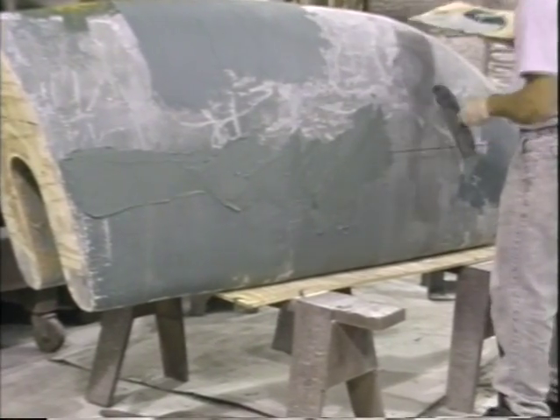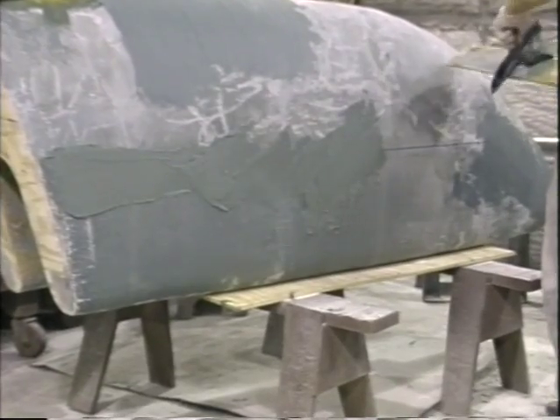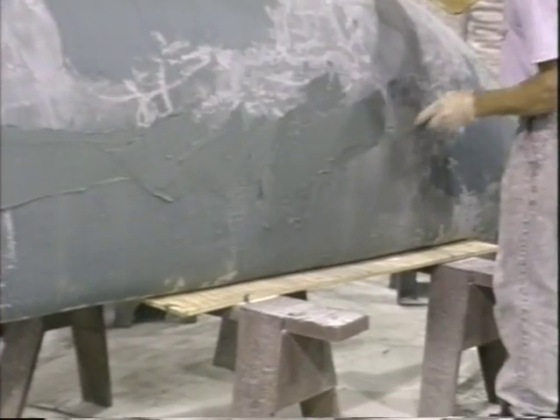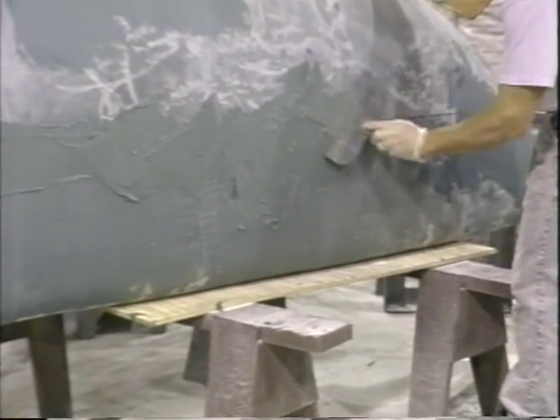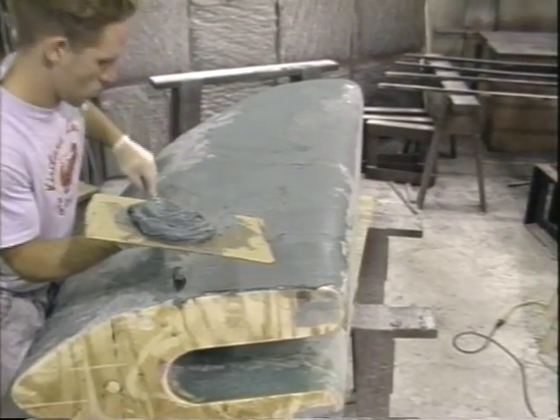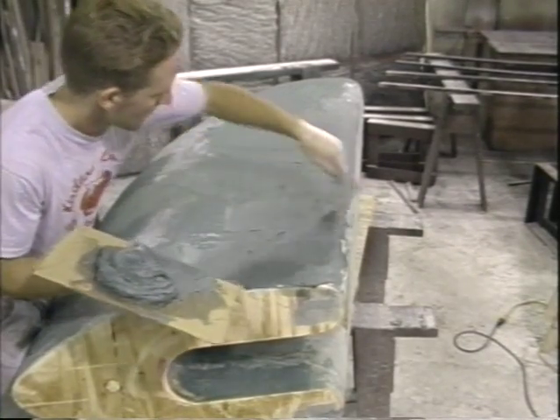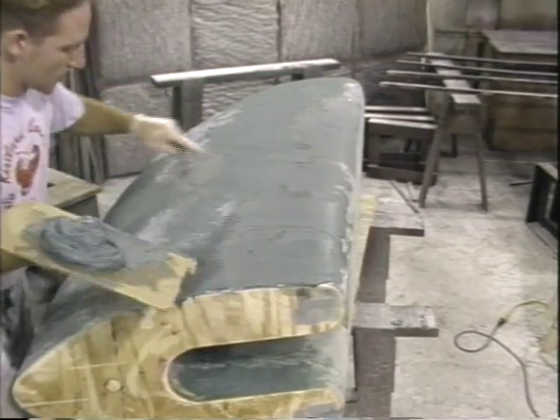Following this line, I built a taper to a height of 3/8 of an inch over a 14-inch span per side using glass reinforced body filler. However, it had to be blended evenly from the bottom of the plug to the parting line and added another week to the project. The desired result was achieved though, and the material added 1.5 degrees of draft to each side of the plug.